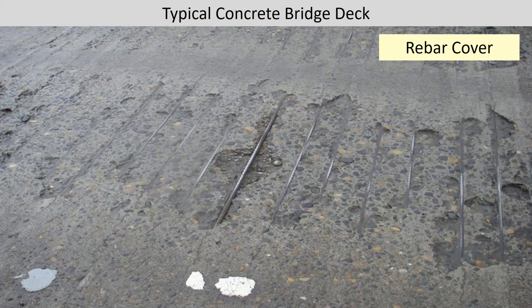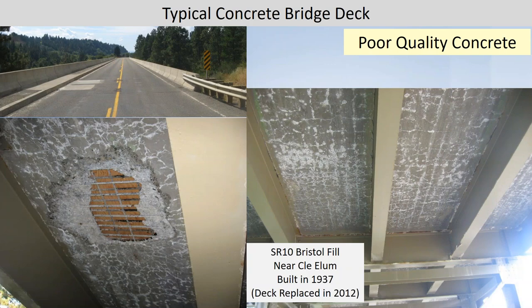So here's a rebar cover issue. If the bridge was built with only about a half inch of rebar cover at one time, over time the wear on the bridge would expose the rebar, and then we have to go back in and fix it with some type of either concrete overlay or another technique. Poor quality concrete: there's just a point in time in the future when the concrete will break down chemically. You can see this bridge was the original Highway 10 before I-90 was put in over by Cle Elum, and it was built in 1937. And so the deck lasted about 75 years, and then because of its condition, we recommended the deck be replaced.